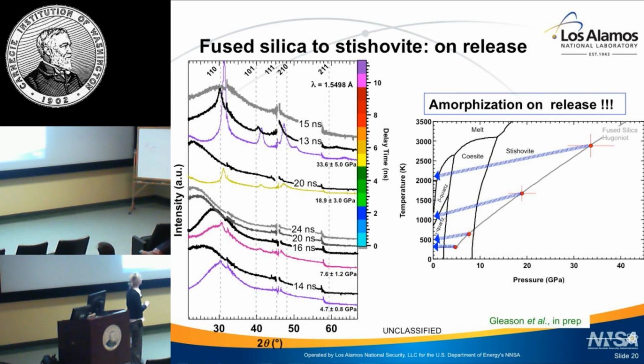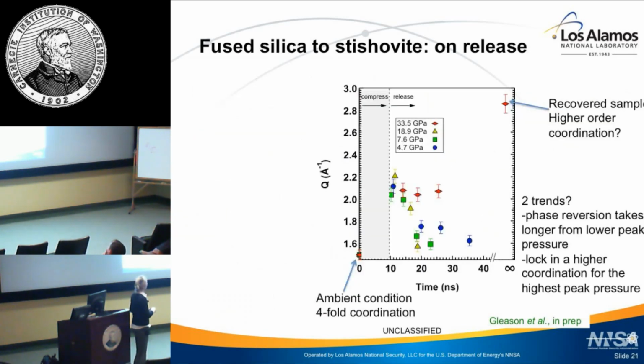Okay, and so here's an example of the path we take. So here's the fused silica Hugoniot. These are my peak pressure states that I achieve, and then upon release, the path that is followed in blue. But we see this amorphization. Moreover, we could collect recovered material, which we do, from, say, our highest pressure state. So here, let me orient you. This is Q, or you think of it as d-spacing, as a function of time. So we start out at ambient condition. We shock compress to our maximum. So here we are compressing, and then on release, we sort of follow 2 different trends here.